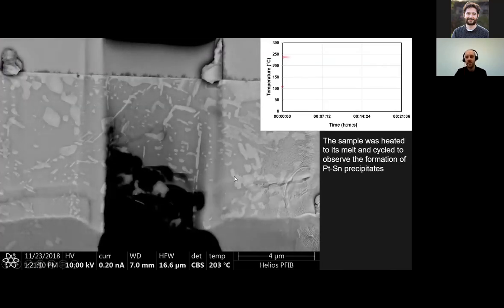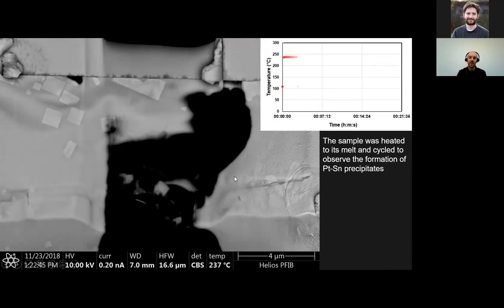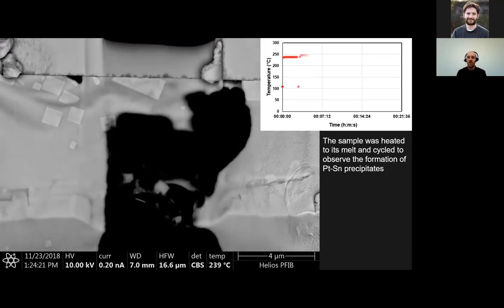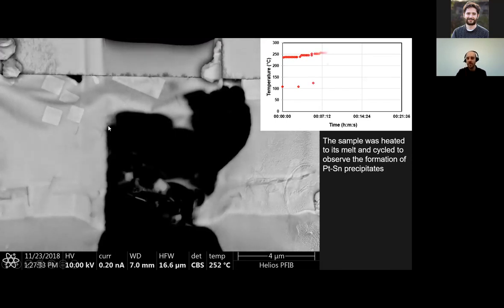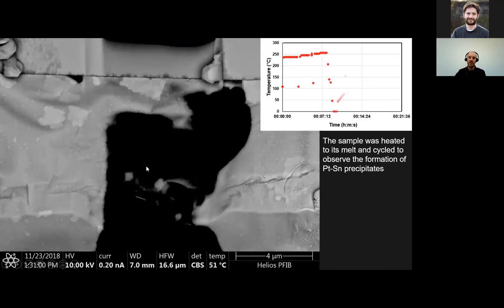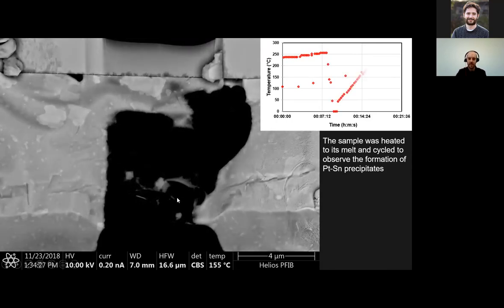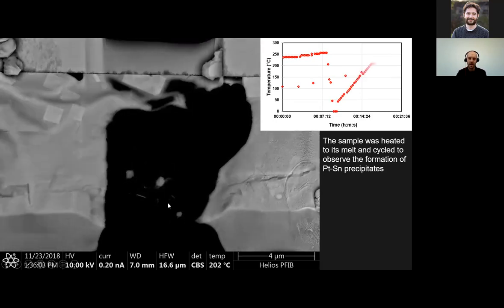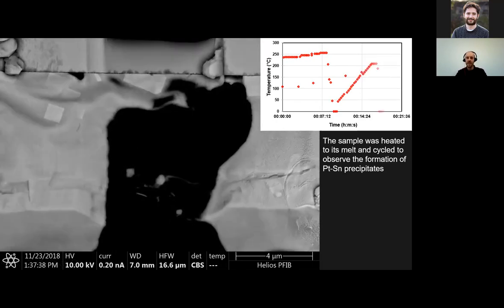Once we had looked enough at the sample, we just had a bit of fun, to see what could be done. We tried doing some thermal cycles on the tin. Here you can see we melted the sample. What's interesting is the sample actually has an oxide layer around the outside. You can see a halo of it here in the middle of the sample, and that seems to be holding the tin as it's molten.